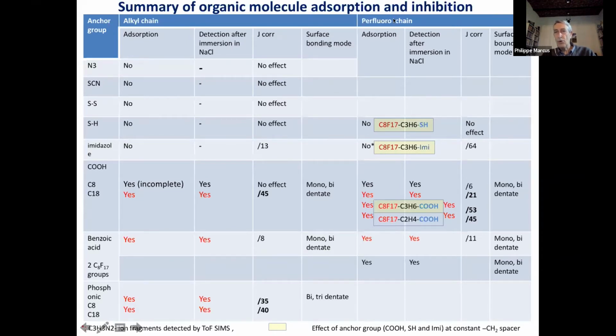If you look at the perfluoro chain, again, there are cases where there is no adsorption if the anchor group is not good. But if the anchor group is okay, like carboxylic groups, in that case, all these perfluoro molecules are adsorbed, and they remain adsorbed after 6 months exposure in sodium chloride solution. There is an additional information, which is the nature of the bonding to the surface, which I've indicated before, could be mono or bidentate in the different cases, or even tridentate in the case of the phosphonic group.